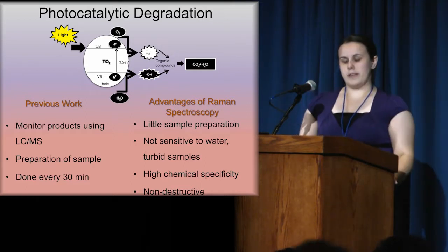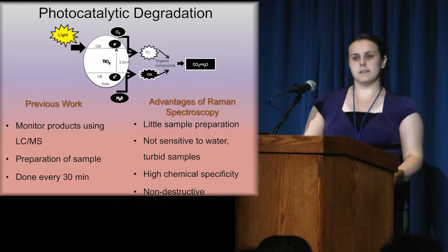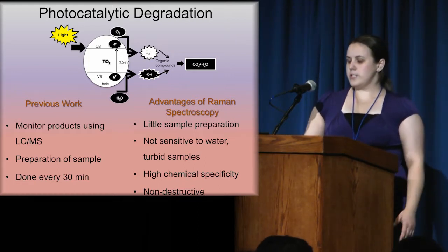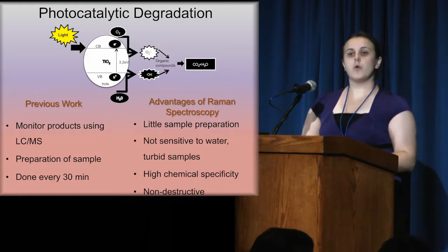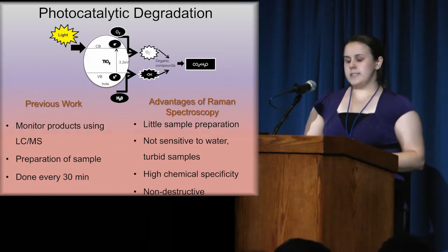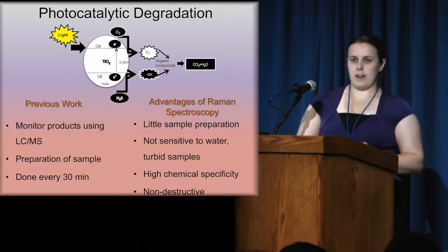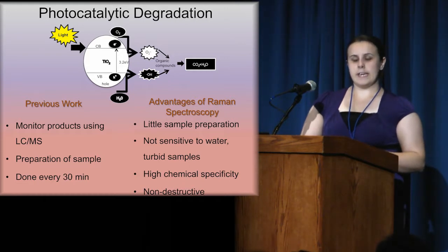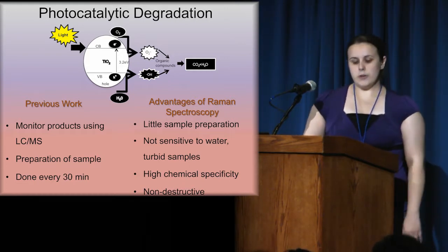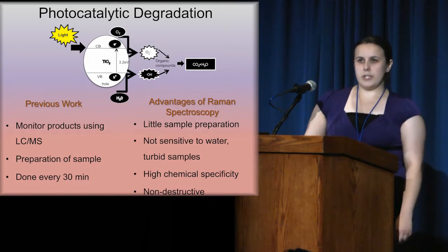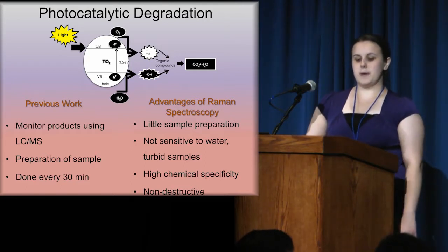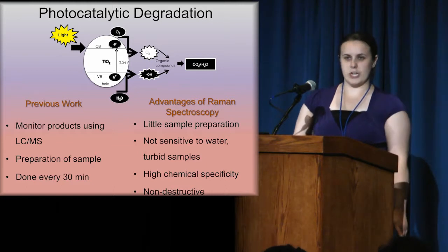We chose Raman spectroscopy because little sample preparation is required, and it is not sensitive to water or turbid samples — which matters because our photocatalyst is suspended in solution. Also, by measuring molecular vibrations, we can connect changes in the spectrum to changes in molecular structure.